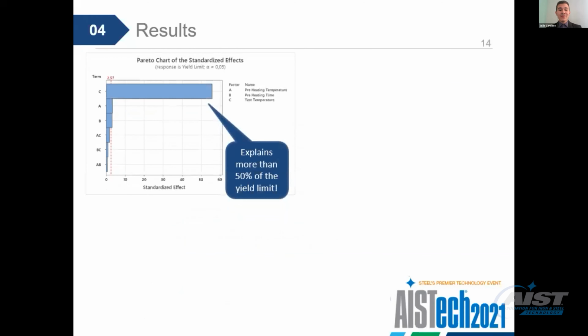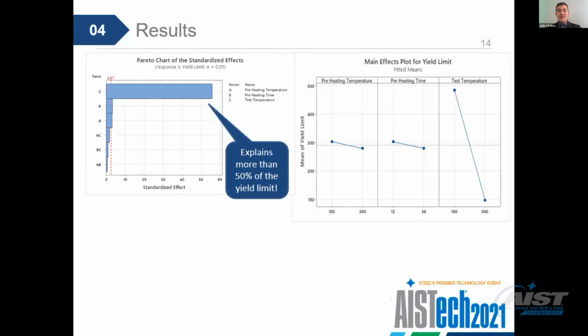As I mentioned, we modeled the response of the variables with design of experiments, and this Pareto chart is the most important visualization that shows the influence of each variable on the yield limit, which is the most relevant property of our study case. As you can see, the test temperature is the most important variable, which explains more than 50% of the yield limit according to the model. The other graph shows the influence of the variables directly on the yield limit. And this visualization also allows us to conclude that the test temperature is really the main variable.